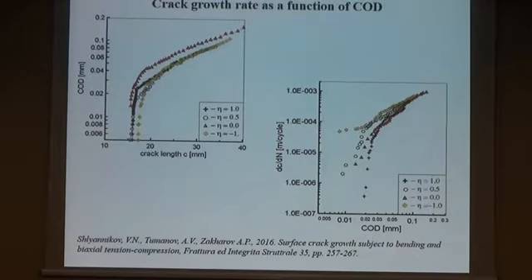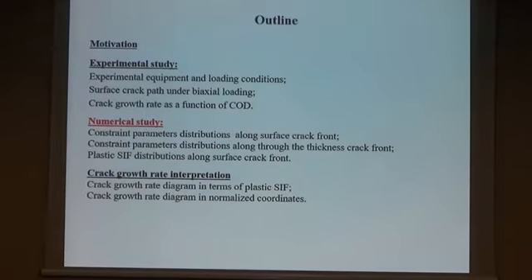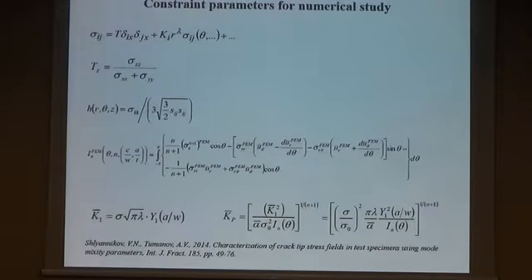So that was experimental results, and now we talk about numerical calculations. Numerical calculations of present study are concerned with stress-strain analysis along the crack front in cruciform specimens for all considered types of biaxial loading, taking into account the in-plane and out-of-plane constraint parameters. And on the basis of solutions for governing parameter of elastic-plastic stress field along the crack front in cruciform specimens, we calculate the plastic stress intensity factors for the crack growth rate interpretation.